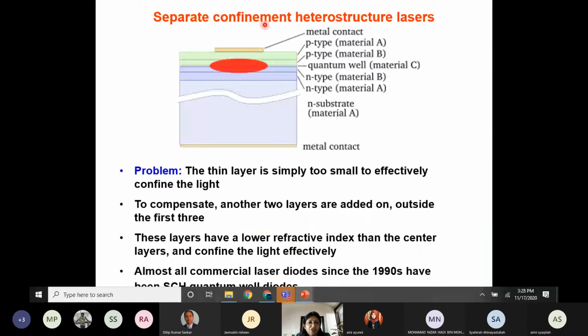So the other structure is the separate confinement heterostructure laser. You see the problem with the thin layer: it is too small to effectively confine the light. So to compensate, another 2 layers are added on outside the first 3. There is a quantum well over here, and you have material C or material A and B added on, and these layers have a lower refractive index than the center layers and confine the light effectively. Almost all commercial laser diodes since the 1990s have been using SCH quantum well diodes. So the optical confinement occurs in one layer, and the recombination occurs in another layer. You can separate it out.